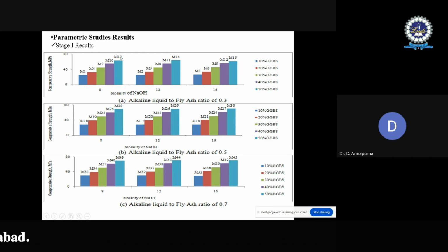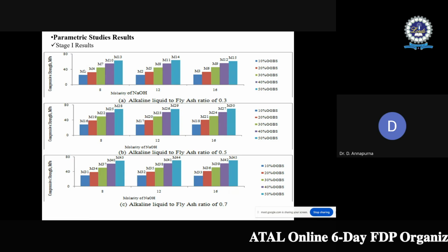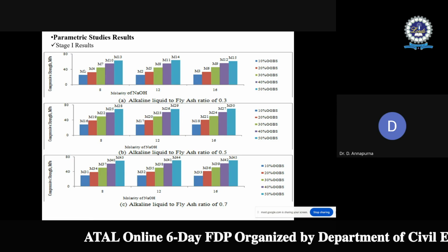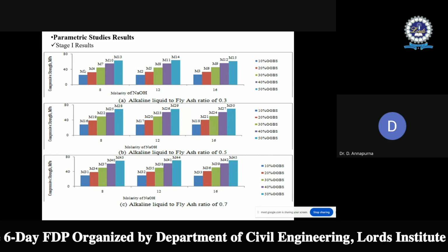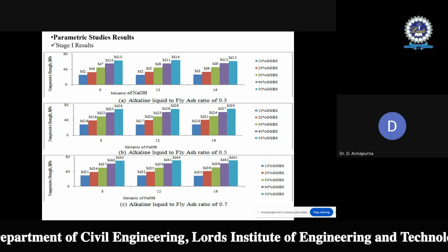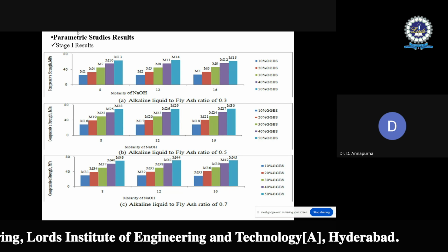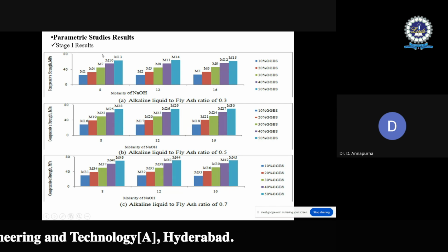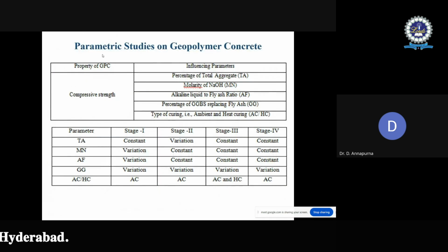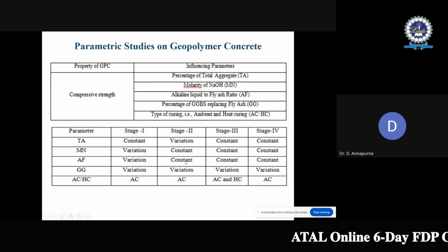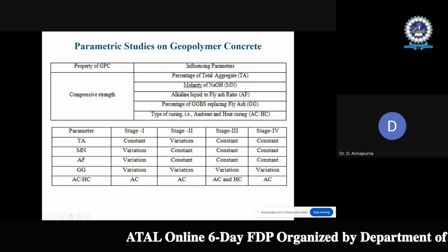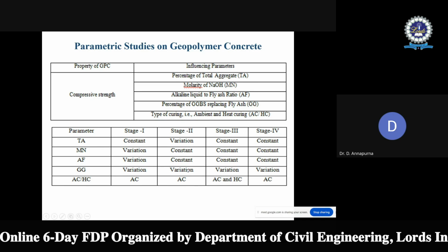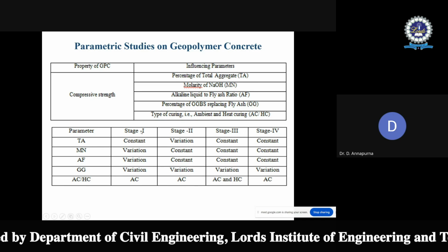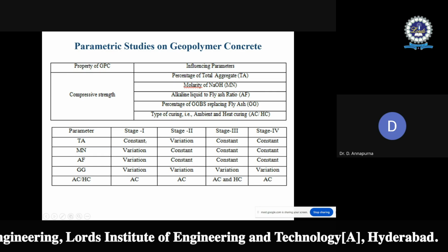So that much tremendous increase in compressive strength is observed with the addition of GGBS. Why? Because, along with sodium aluminate silicate hydrate gel, it also gives calcium silicate aluminate hydrate gel. That is the reason it gives a huge amount of compressive strength. Keeping that in view, for the next stage of investigation, the GGBS dosage is maintained as a variable, because it gives improvement in the strength. Then in the first stage, the total aggregate content was maintained constant at 70%.